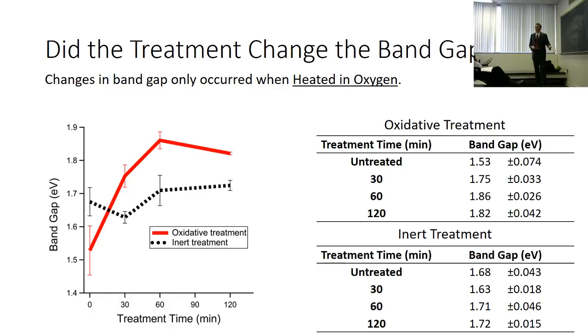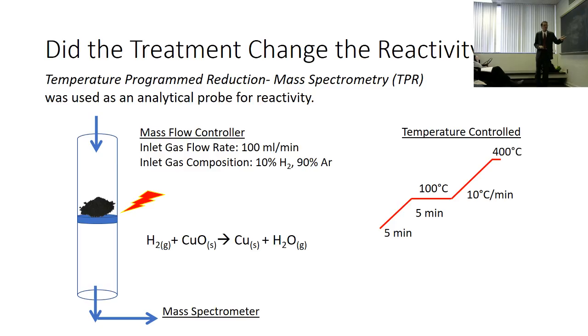Second mystery. But I wanted to go play with my reactor. I had my hypothesis—I found changes in band gap. The second piece was changes in reactivity. So I did something called TPR, hydrogen TPR, to test the reactivity. This is a probe sort of reaction. Copper oxide is a mild oxidizing agent, hydrogen is a strong reducing agent. When you heat up copper oxide in hydrogen, the hydrogen sucks out the oxygen from the copper oxide.